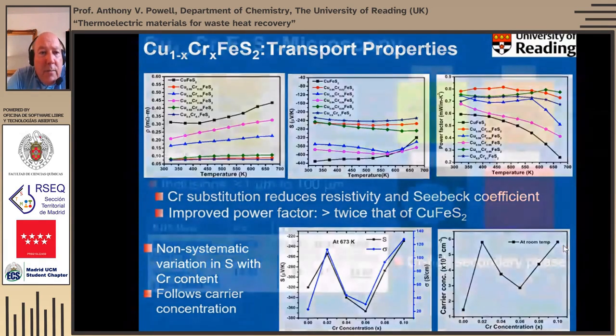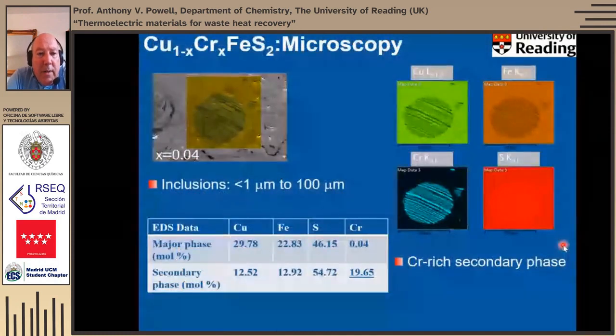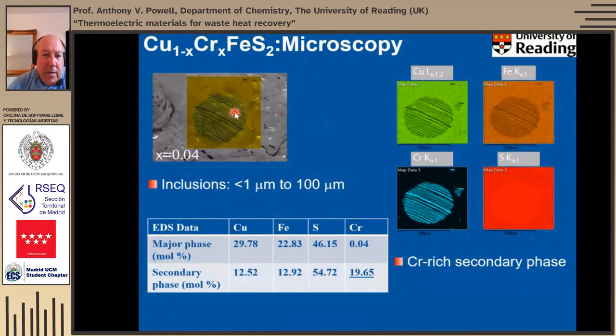So that really led us with our colleagues at Manchester as part of the project to look at the electron microscopy. And what we find is we find inclusions within these materials. This is just one composition here. This is 4% chromium. We find inclusions over quite a wide range of length scales, from the sub-micron level up to quite large inclusions like this one, which are almost 100 microns.